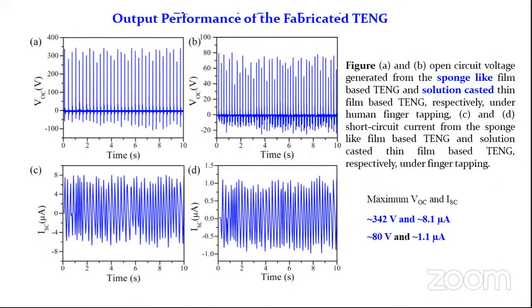After fabricating the device, we have checked the output performance of the nanogenerator. We have also compared the output performance with the solution casted film. We have seen that the solution casted film only produces 80 volt, whereas the sponge-like film produces 342 volt. So that means a huge increment when we have the sponge-like structure. It is also proved from the current measurement. As you can see here, 8.1 microampere current was obtained from the sponge-like film, whereas 1.1 microampere current was obtained from the solution casted film.